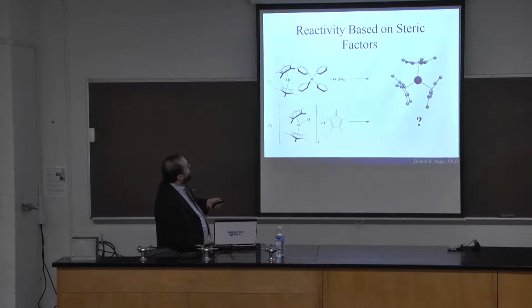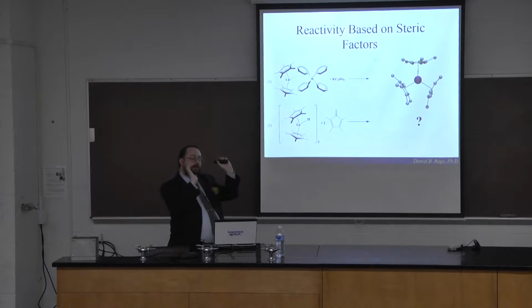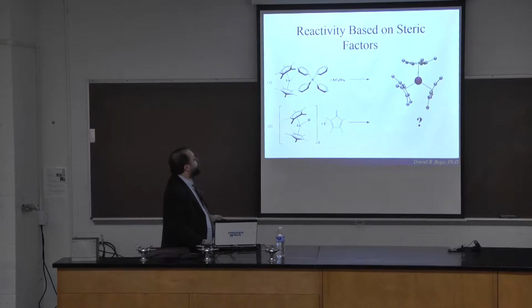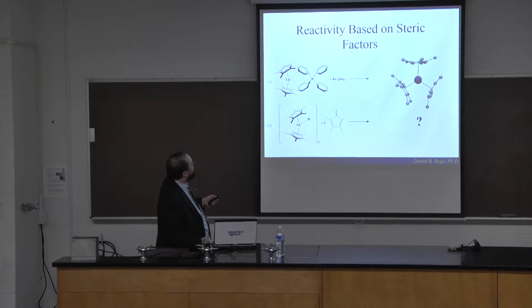So, for example, this is a tris(pentamethylcyclopentadienyl) compound around the lanthanide. This is 3+, each one of these ligands is 1-. This is a very sterically oversaturated molecule, kind of hard to get these three bulky rings all around the metal. There are two methods of synthesizing this, well, more than two, but just two, for example, here. One, you're basically replacing this tetraphenylborate with a pentamethylcyclopentadienyl from a potassium salt, or alternatively, you can start with hydride, to add the hydride to this organic fragment to form a pentamethylcyclopentadienyl, thus forcing it to coordinate.